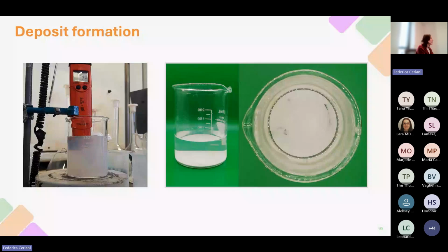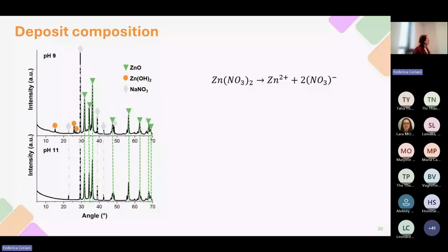Chemical composition of this deposit is analyzed through XRD test, and here in the slide, 2 diffractograms are reported. The upper one is related to a deposit produced in a solution having a pH equal to 9, while the lower one is related to a solution having a pH equal to 11. We could observe that in both the cases, the main constituents that are found are zinc oxide and sodium nitrate. However, there is a significant difference between them. Indeed, for a deposit produced in a solution having a pH equal to 9, even zinc hydroxide is found.